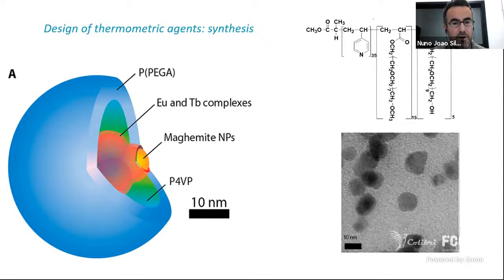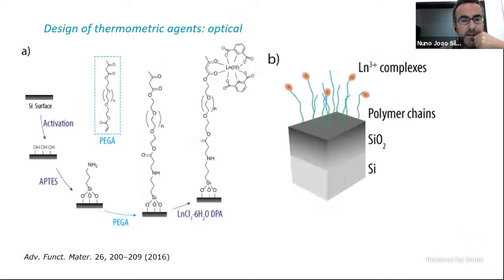The maghemite nanoparticles, it's a standard method. You have iron salts in a water solution, and then you increase pH. And when you increase pH, you first form the hydroxides, and then you start condensing hydroxides, you release water, and you get an iron-oxygen-iron bond, and you have your nano iron oxide. So this is how we made these thermometric beads, these thermometric nanoparticles. And we went to another design.